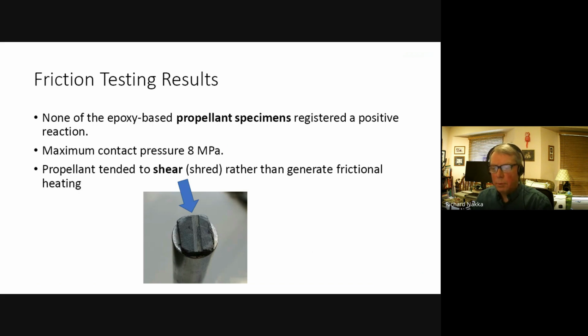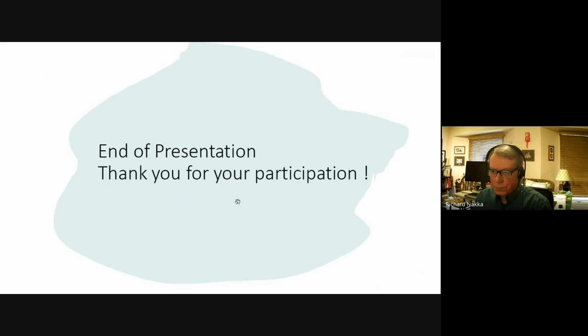Then I tested all the propellant specimens, and the good news was there were no positive reactions, even though I used a contact pressure as high as 8 megapascals. The propellant tended to shear or shred rather than generate frictional heating. So this picture shows an example of a tested specimen. And that's the end of my presentation.